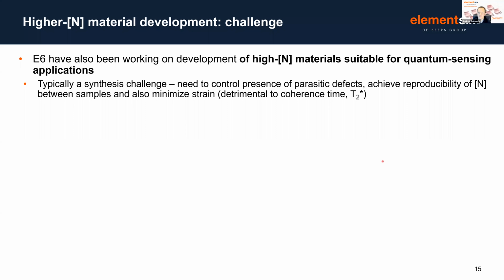So at the same time, as mentioned in the earlier slide, we've been working on higher nitrogen containing materials at around 10 parts per million. Now this is typically a really challenging area for people to grow nice diamond samples. And this is really because you need to control the presence of what I'm going to introduce as parasitic defects that can affect the coherence time and contrast. You also need to achieve reproducibility between the samples and control strain in the diamond material, which I'll explain shortly. And that's also detrimental to coherence time.